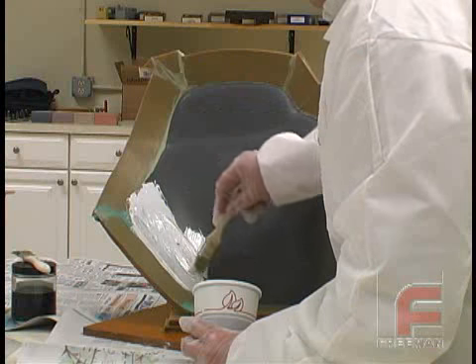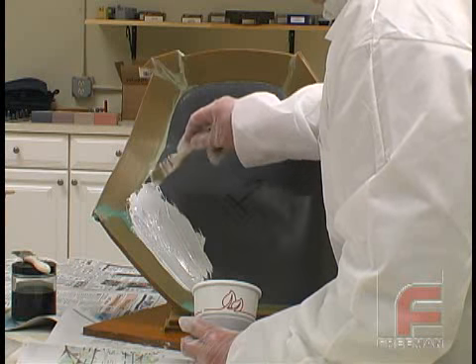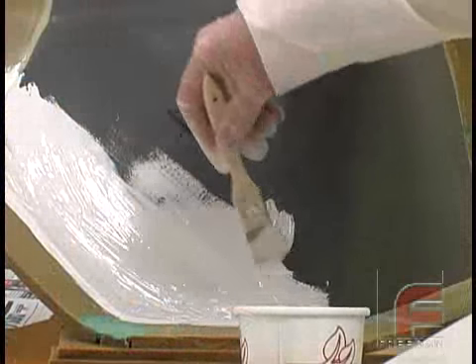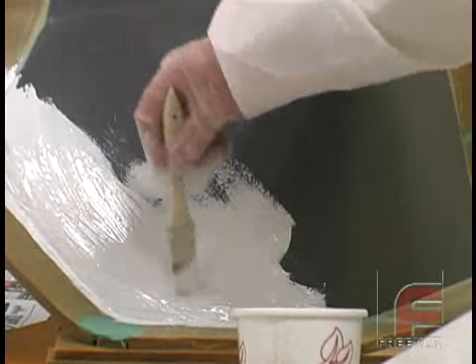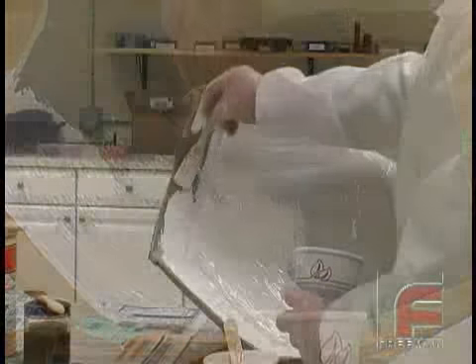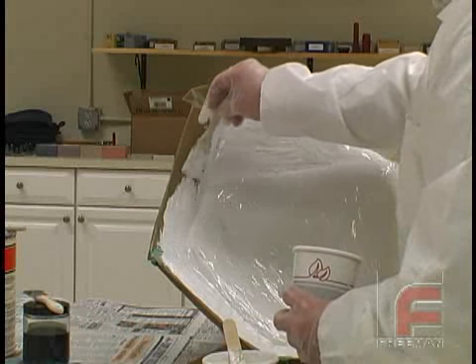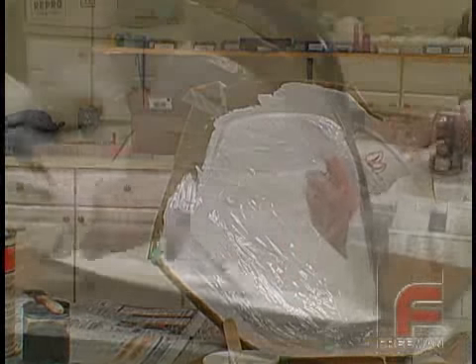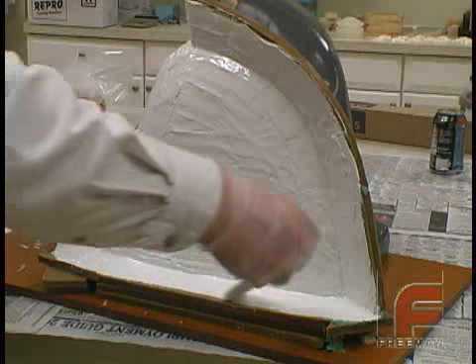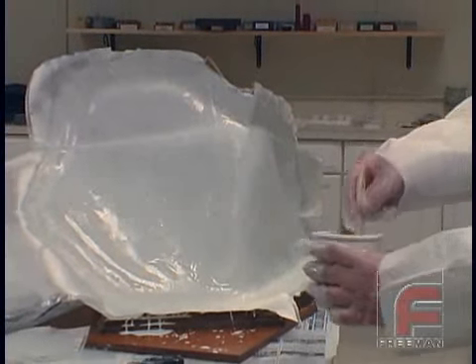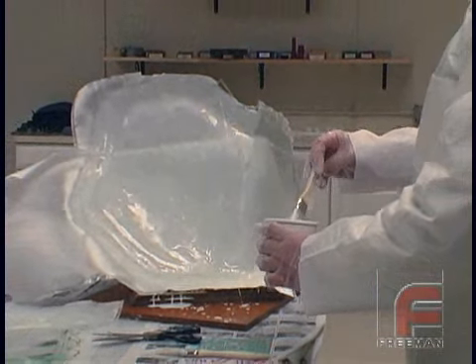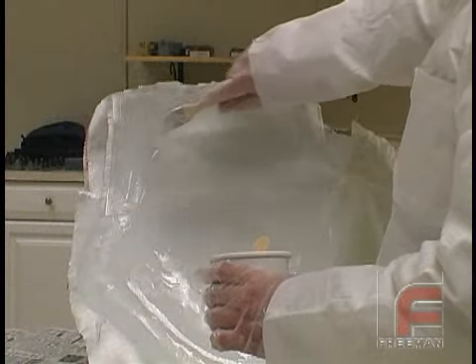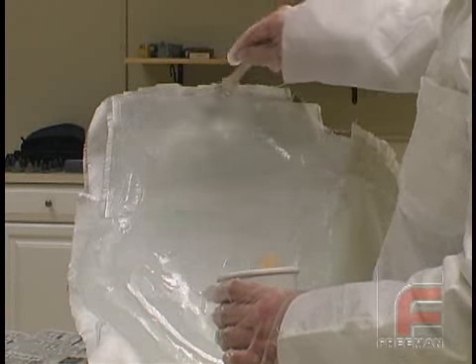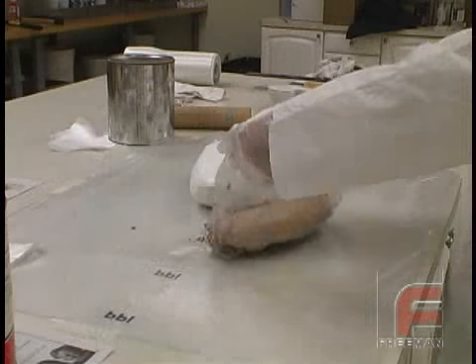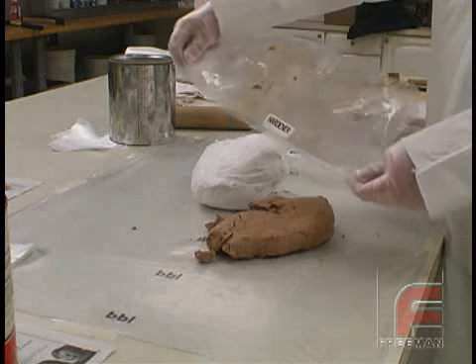The first step of the paste laminating system involves applying two layers of surface coat, such as our Freeman 705, with a cut brush. As always, we wait for the material to reach the almost tack-free state before applying additional layers. The next step is applying three layers of laminating resin and fiberglass cloth, plus a final layer of resin that will act as an adhesion layer. Since we devote an entire video to epoxy laminating systems, we won't repeat those instructions here. After three layers, we are now ready for the paste laminate material.